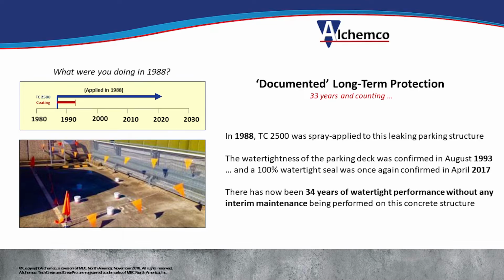So it was a leaking parking structure. They had a bunch of cracks. And after the material was applied, they did the first test in 1993, so 5 years later. And they were able to verify that the area was completely dry.